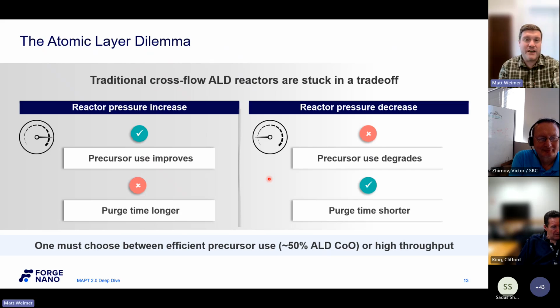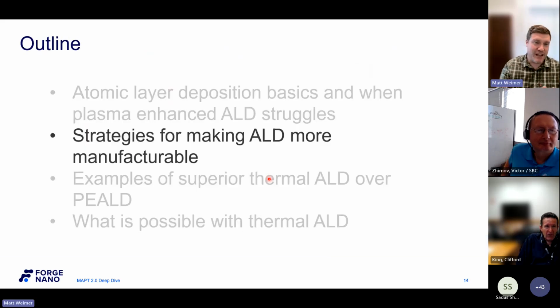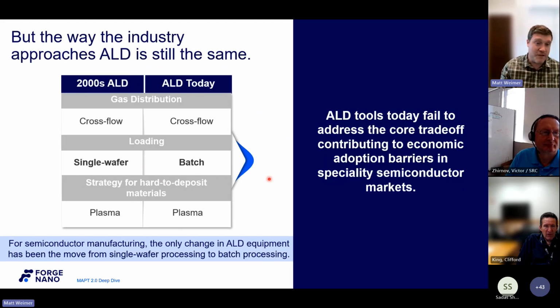So people in the ALD world know this, and they've tried a lot of strategies to overcome this. One is to simply put more wafers in a reactor, go to a batch tool. So here you have 25, 50, 100 wafers. And there are some engineering challenges there, but people have overcome those for the most part. So you can actually improve your throughput with a batch tool. But the biggest downside is if something goes wrong and you have 100 of your wafers in that tool and you push stop, that's a big oops, right? You're scrapping a lot of expensive product. So, typically in the 300 millimeter space, people prefer single wafer.